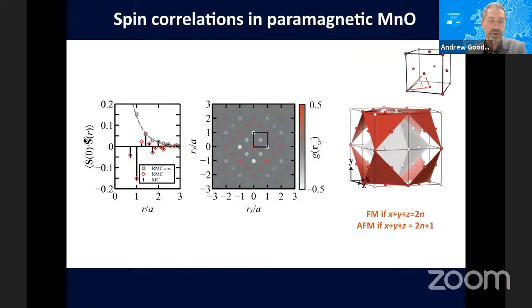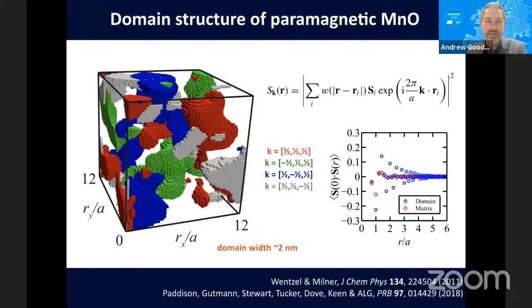So for example, in this case, you can plot a spin correlation function. You can see that nearest neighbors and then next nearest neighbors are antiferromagnetically coupled. And you can look at more complicated orientational dependent spin correlation functions. This is the one I like. You can take your box and you can start to look for the extent of local ordering. And really the question you might be trying to answer here is, if you're in a paramagnetic state, at some temperature above the Néel temperature, is it the case that the magnetic order that persists, this local order, is it uniform, or is it the case that you have regions that are more strongly ordered than others? And if so, what are the sorts of sizes of those regions?